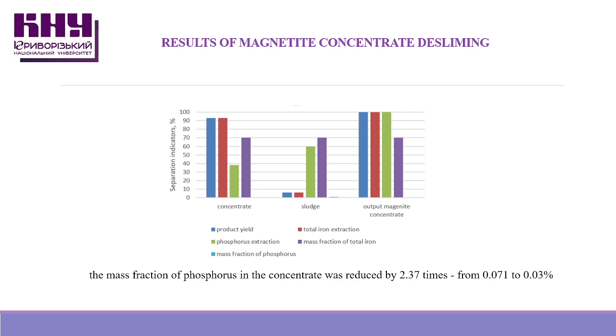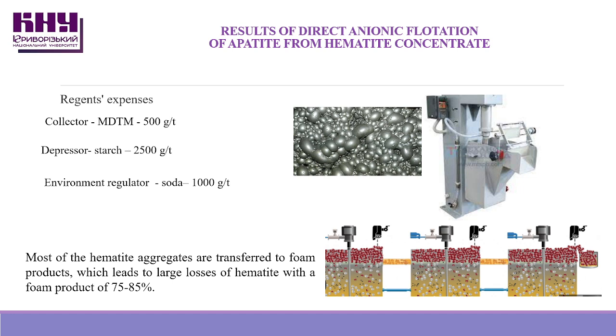flotation of apatite. The desliming operation of magnetite reduced the mass fraction of phosphorus from 0.071% to 0.03%. During the second stage of research, direct anionic flotation of apatite was performed on the hematite concentrate sample. The best indicators for the dephosphorization were obtained at the consumption of reagents: MDTM 500 grams per ton, starch 2500 grams per ton, soda 1000 grams per ton.